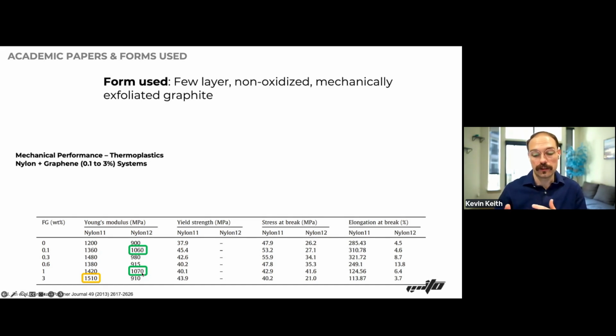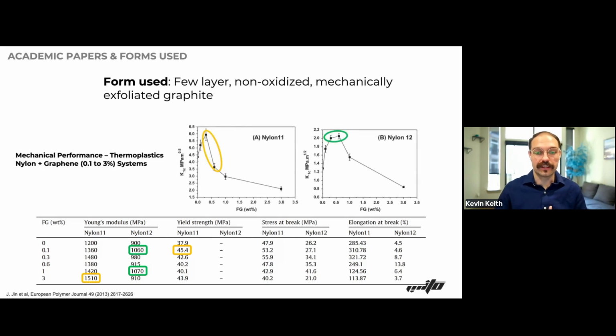And that's because of the metrics that you're using to qualify what that few layer non-oxidized mechanically exfoliated graphite was enacting on the system. Nylon is a really interesting material in the fact that when you load graphene into it, it can get really touchy depending on what graphene material you load into it. So you have to really watch out what you're putting in there. Same thing. So here you'll see those graphs that within nylon 12, 0.5, 0.1%. This is the same graphene material loaded into both of these plastics, but you still get drastically different properties, even though you know what levers are being pulled, but then it's interacting totally differently with the system because of how that graphene is made.